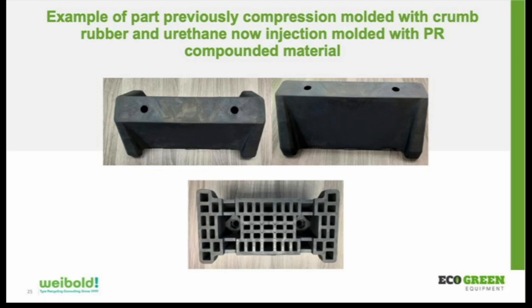So again, the point of this particular application is we've taken a compression molded part, which is where you're mixing crumb rubber and urethane, putting it into a mold, compressing it under heat and pressure for maybe as many as 15 minutes. Then you open the tool, dig the part out, and you have a compression molded part. This part's able to be made in about 2.5 minutes. This is a two cavity mold, and this one two cavity mold on a big injection molding machine was able to outproduce four compression molding stations that were making multiples of these.